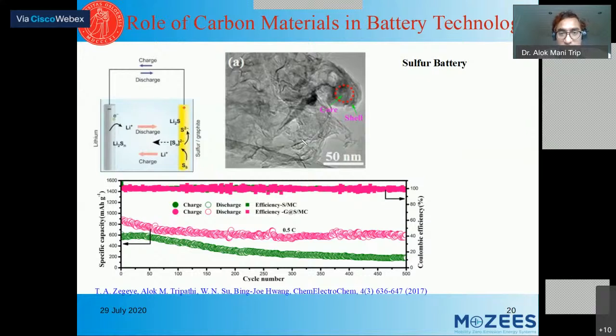Here is one of our research works where we used carbon, and in the carbon we impregnated the sulfur, and then it was supported with graphene. What we find is that if we don't have the carbon and other things, it loses capacity. And this is 500 cycles of the run. When we use carbon and graphene both together, the stability is very good. We are getting 800 milliamp hour stable capacity up to 500 cycles.